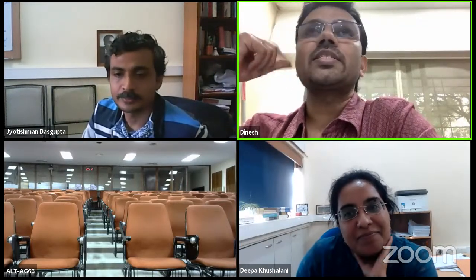Deepa, please. Just a very quick one: the cryo work is quite intriguing, that you're able to see these lattice fringes. How does the film thickness correspond with what you're seeing in cryo to what you think is in reality? So these film thicknesses are in the range of something like 80 to 130 nanometer.